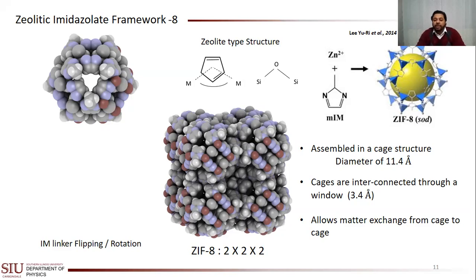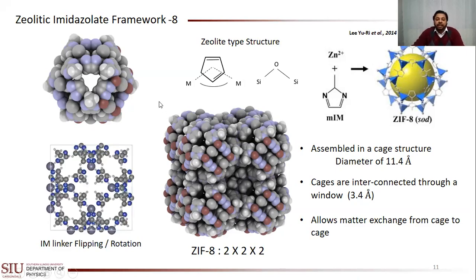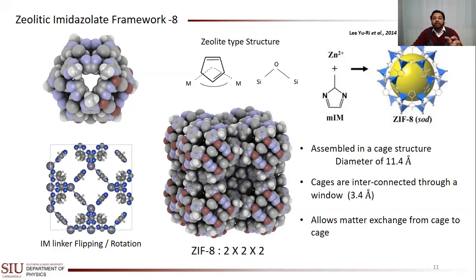So these openings and this hollow cage structure actually allow material or gases inside the structure, and it can store them within, like a sponge. So that's the uniqueness of this ZIF-8. Another prominent characteristic of this ZIF-8 is its linker rotation. It can swallow a bigger molecule by making the linkers rotate in a certain direction and make the opening a bit bigger.